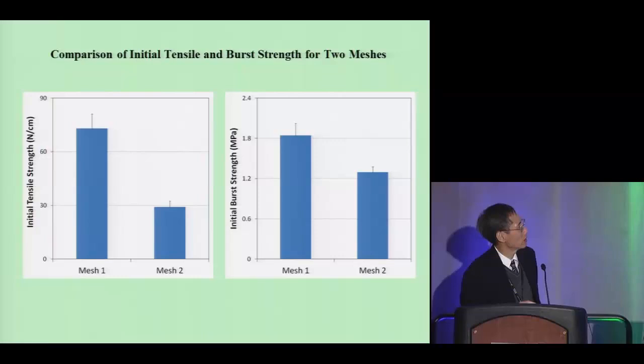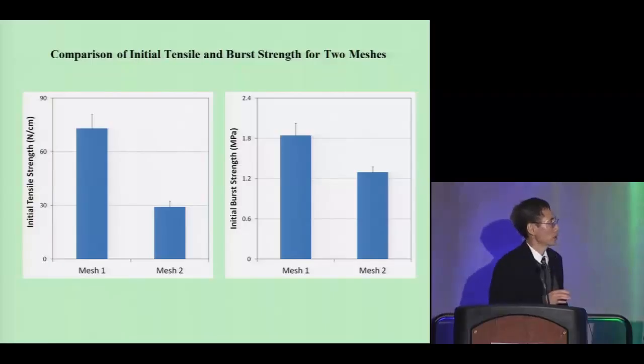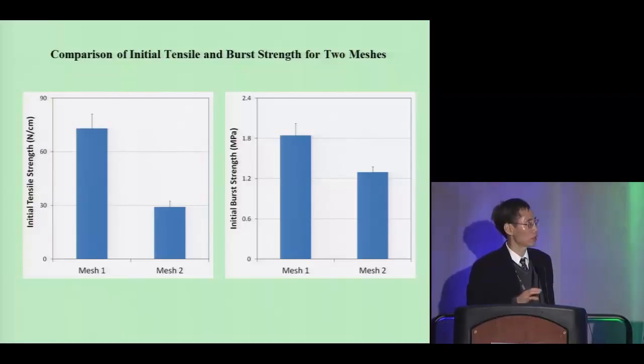These two plots show the strength comparison for the two meshes. For tensile strength, we normalized by the sample weight. I also want to point out the test we used is a little different from the ASTM standard. The reason is that the ASTM standard calls for a quite large specimen size, but for many studies we want to put these materials into animals, so there is a restriction on the sample size we can implant into the animal. However, we showed this test's repeatability is quite good. As you can see, the error bar is small.